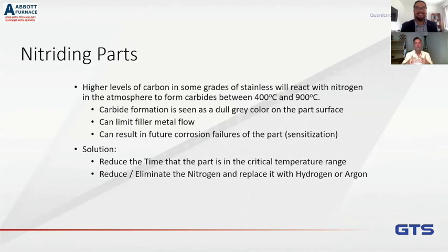Well, the problem is if you have nitrogen in there and you do what's called sensitization, instead of all of the chromium being connected with oxygen, you could have a nitrogen atom in there, and it doesn't form that nice sealed layer. And now it can allow air to go through that layer and get to the base metal. The scary thing is oftentimes people will not see this, and they'll ship because it's not visible to the eye, and they ship it to the customer, and only after it has been put into service, it starts to pit. And you'll see that the part will start to corrode, and then they'll call you up.